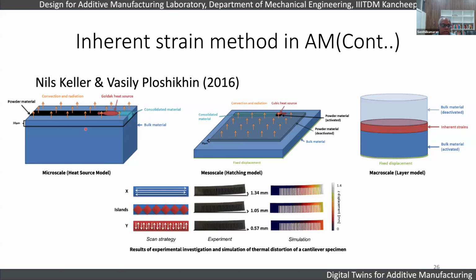So here you can actually do a micro scale heat source model and a mesoscale hatching model. Then you can take those inherent strains measured from the cubic heat sources and put those inherent strains here. So you have a bulk material for the individual layer. You can actually do the inherent strain in the macro scale layer model. So this is done using simple experiments.